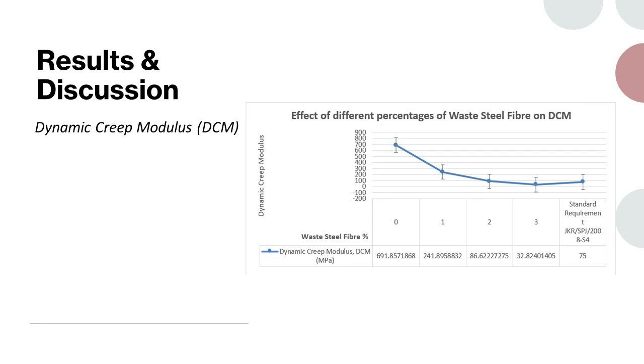This indicates that higher WSF content is associated with a reduction in the dynamic stiffness of the asphalt mixture. In simpler terms, the asphalt mixture with higher WSF content exhibits lower resistance to deformation under dynamic loading. The decrease in DCM values with increasing WSF content suggests that adding waste steel fibers affects the interlocking and binding characteristics within the asphalt mixture. Fibers may create discontinuities or disruption in the asphalt matrix, decreasing the overall dynamic stiffness and causing a higher susceptibility to deformation under dynamic loading conditions.